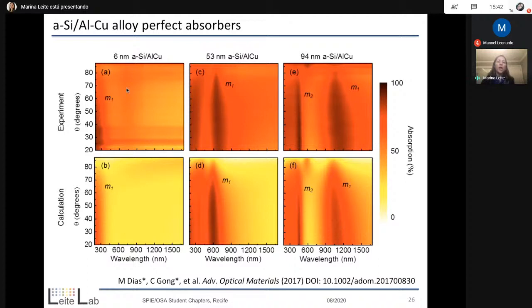But essentially in this case, we had an amorphous silicon and then in the back, an aluminum copper mixture. And so you can still see here the excitation of an optical mode. In this particular case, if you go thicker in the amorphous silicon layer, you can see M1 and M2 now. So I think this is a really nice semi-quantitative agreement, at least qualitative, of how we could now be looking at these metals, metallic mixtures, more closely for superabsorption.